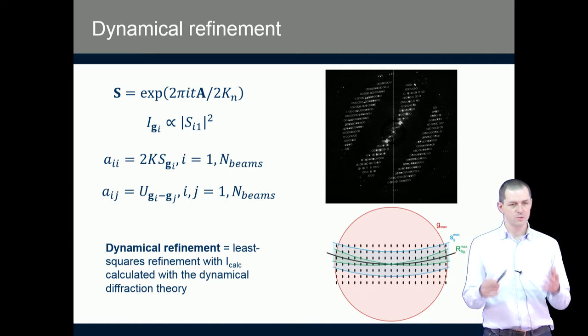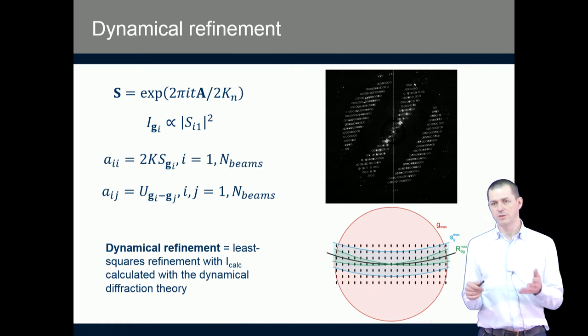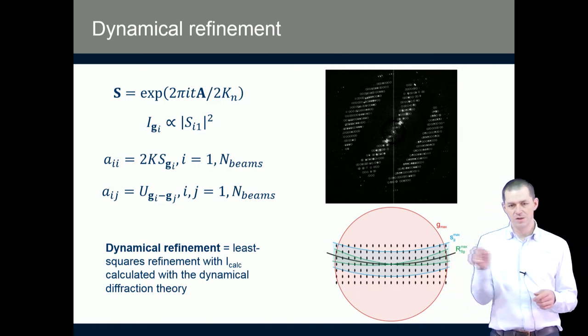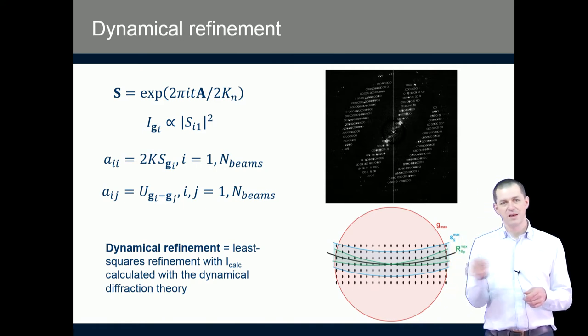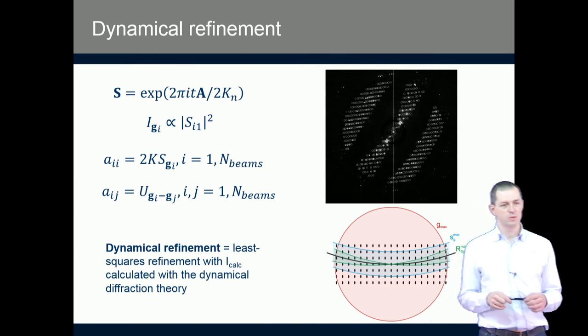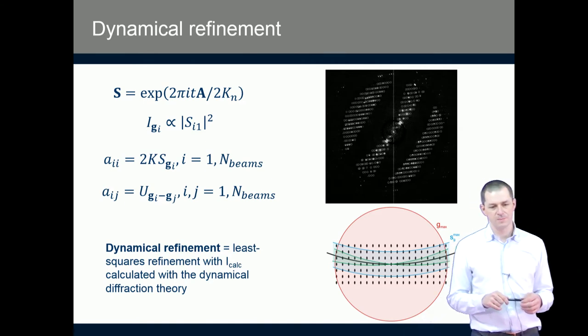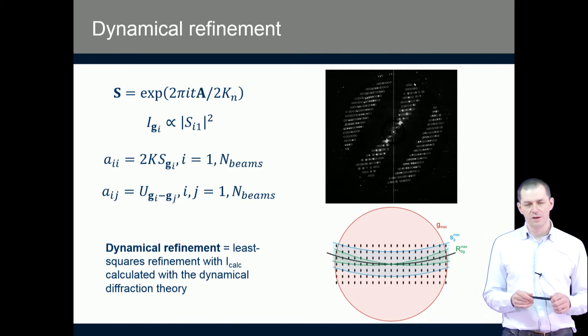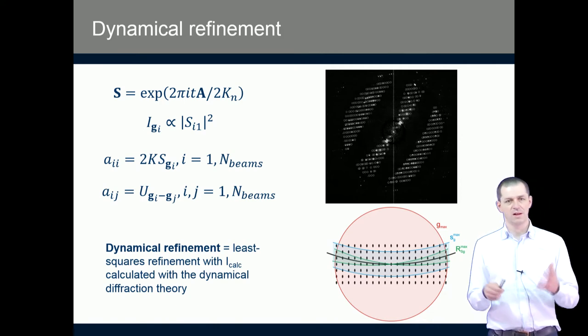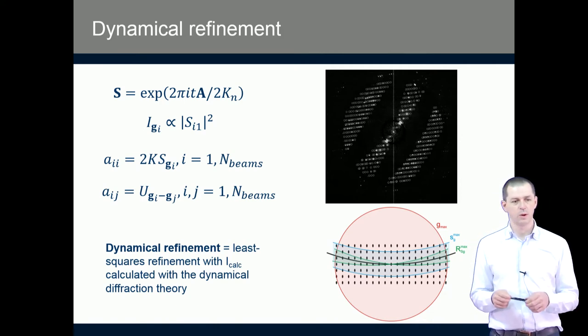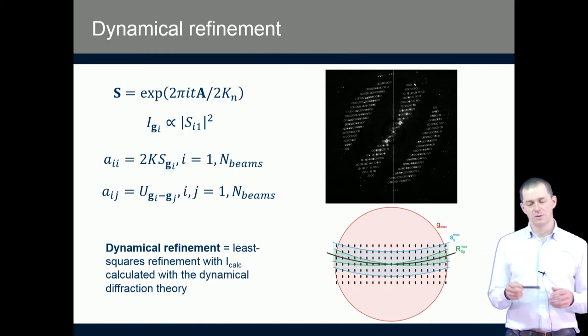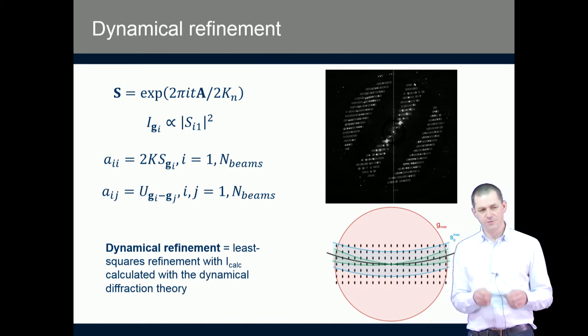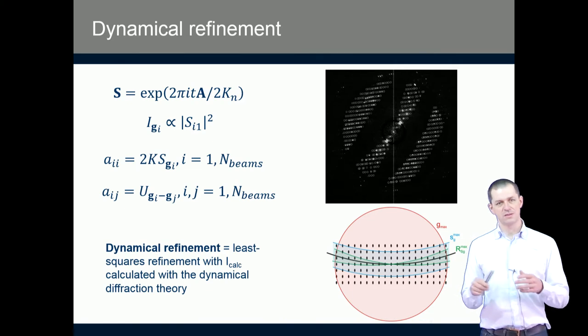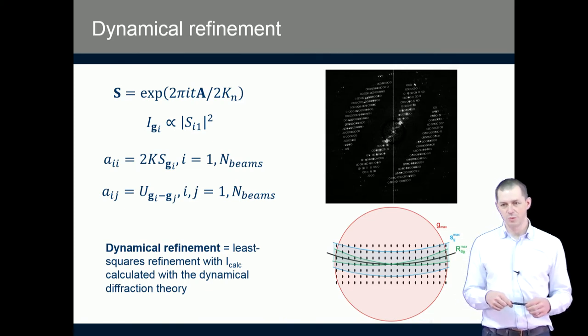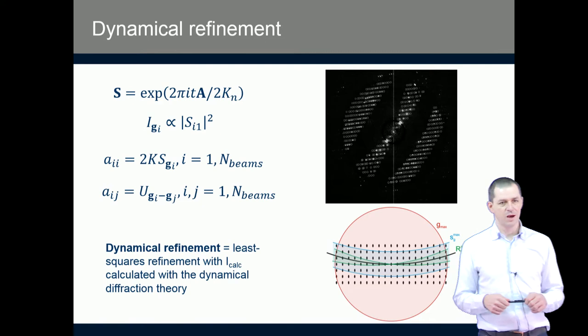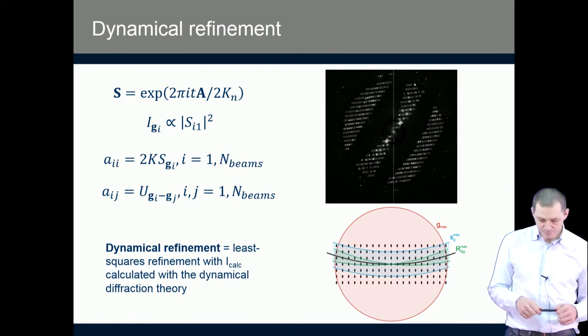So in X-ray diffraction, when you start refinement with Jana, you see the cycles go like this. In electron diffraction, as you will see today afternoon in the practical session, it may be something like, for a simple structure, 1 minute per cycle. So it's not as fast as X-rays, but it's still acceptably fast. You can get results within hours or days.